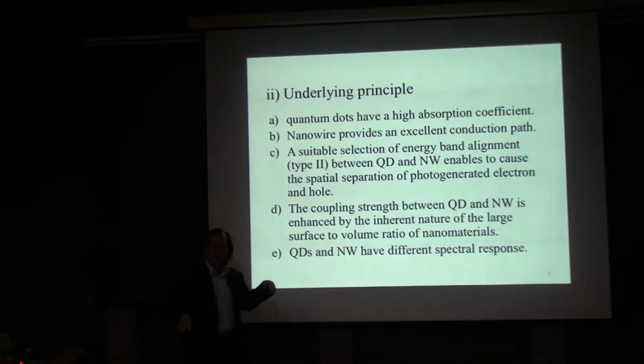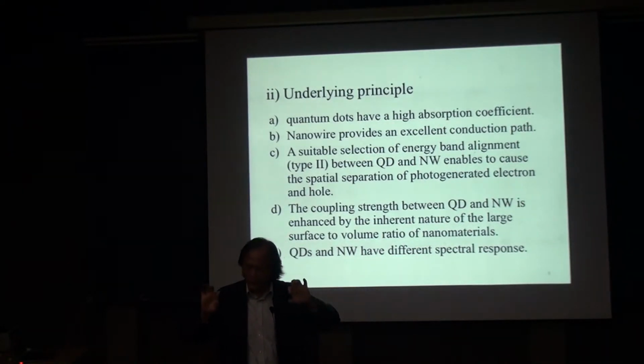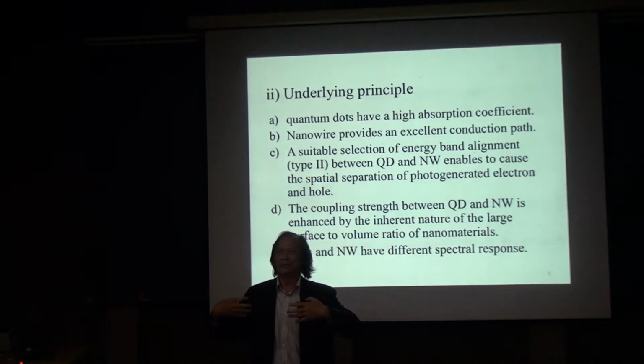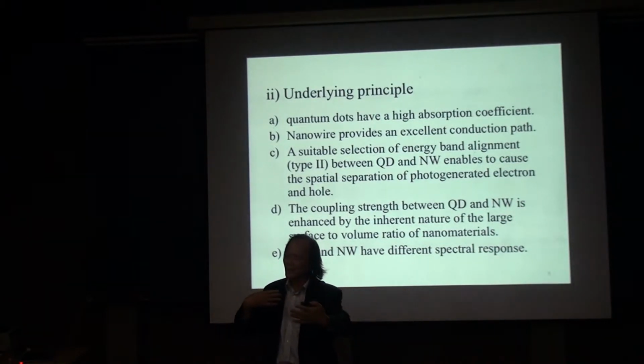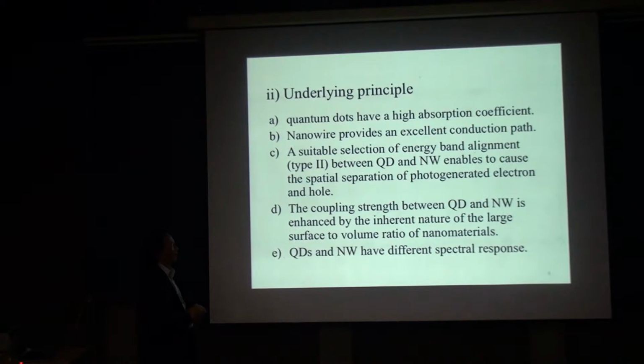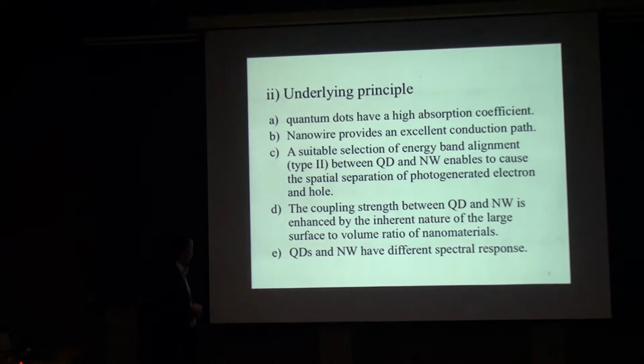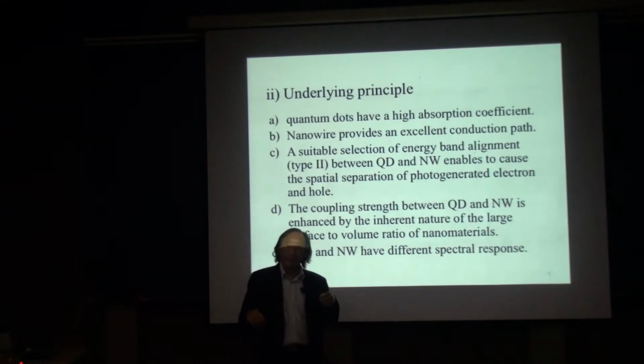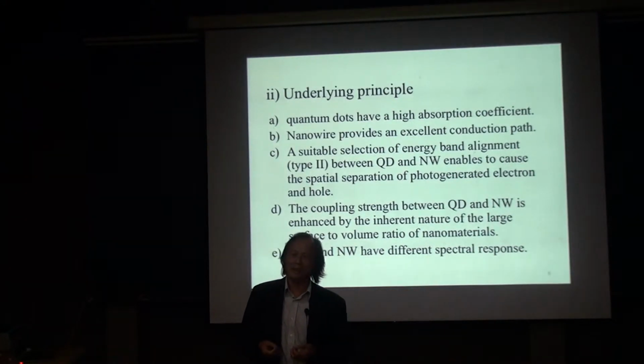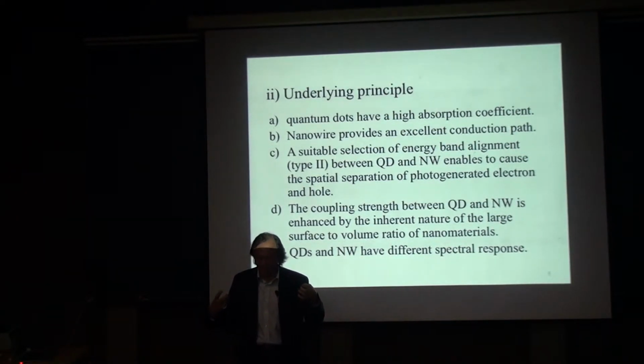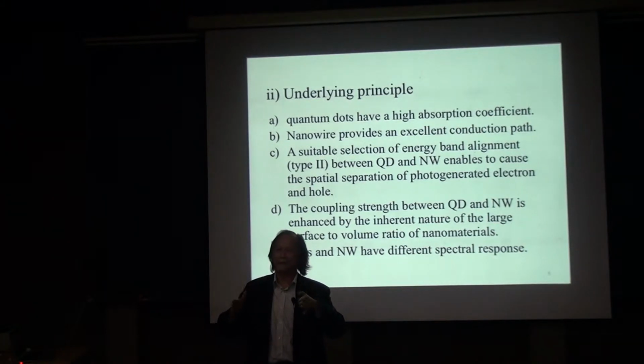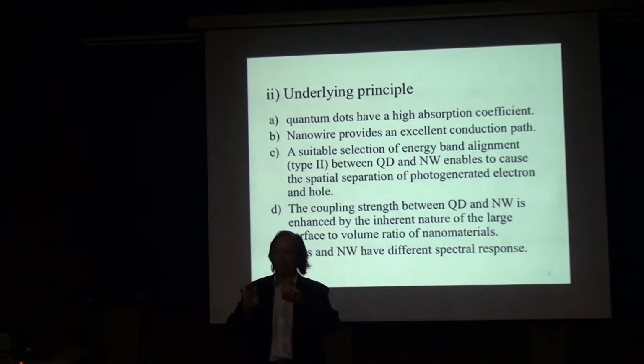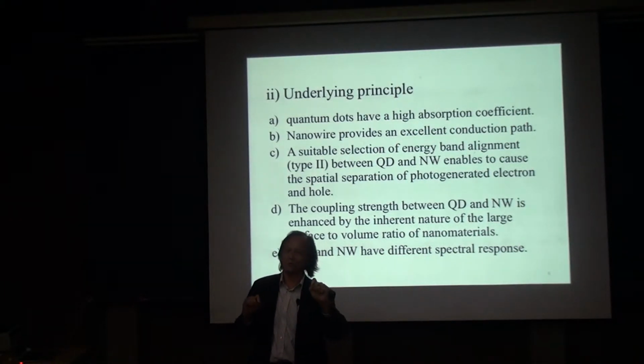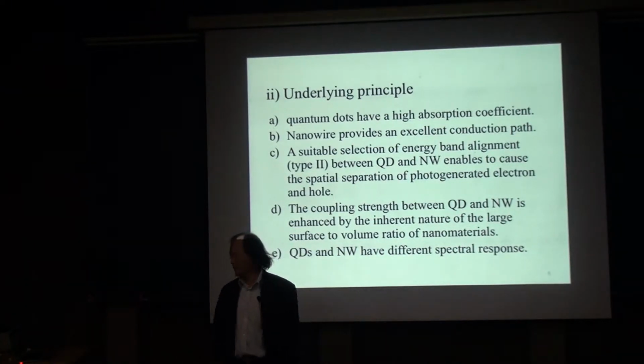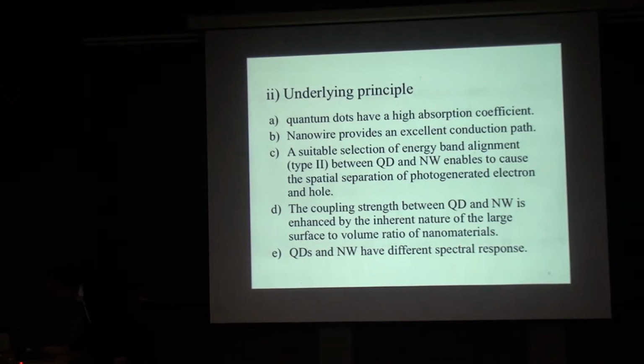And the fourth one is, because we know nanostructured material has a large surface to volume ratio, the coupling strength between the quantum dot and the nanowire can be enhanced due to the nanostructure of the material used. And the last one is that the nanowire has a different spectrum response from the quantum dot. Putting them together, the spectrum response comes from both the nanowire and the quantum dot. Therefore, the spectrum response can be greatly enhanced. Okay, that's the underlying principle of our device.